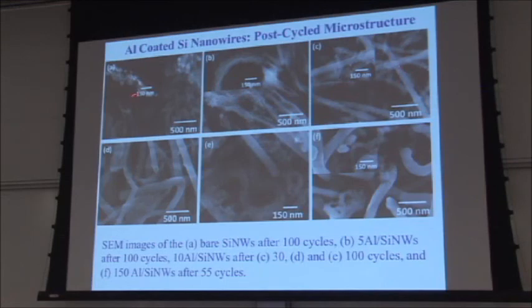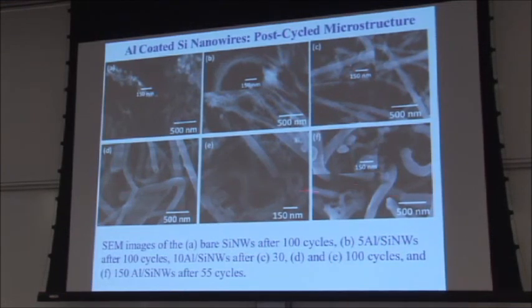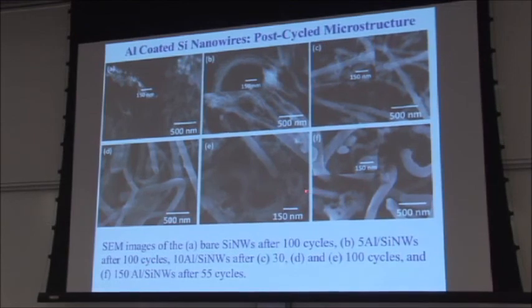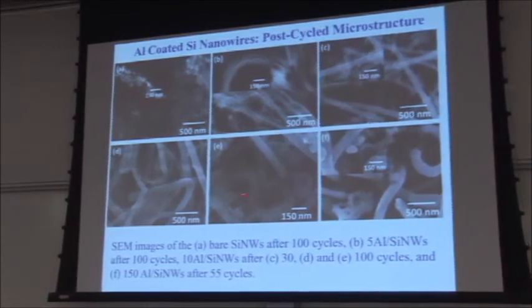So compare this to this. Again, this coating unfortunately didn't penetrate all the way to the bottom. You have shattering, but essentially there's a very noticeable difference in the microstructures. And interestingly, the thicker coating seems intact, but I'll actually show you that in fact it's not. Where you're looking at the aluminum and not really seeing the underlying silicon.